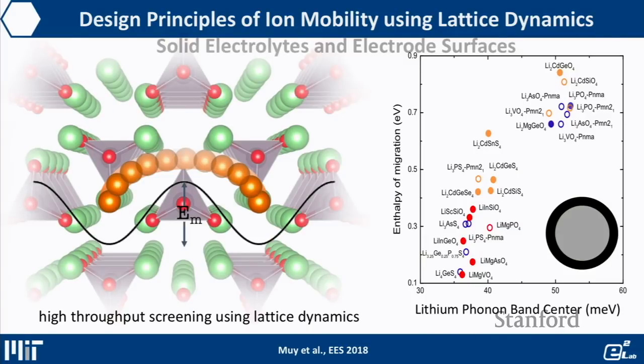What we find on the right-hand side is that the migration barrier essentially correlates with the lithium phonon band center, or the average vibrational frequency of lithium in that particular lattice, right? So across a large number of compounds, not only in the LISICON structure, but also in the olivine structure, right? So this is what we find to be one of these first universal design principles. You can play with phonon density of states that you can influence and dictate lithium mobility, right?